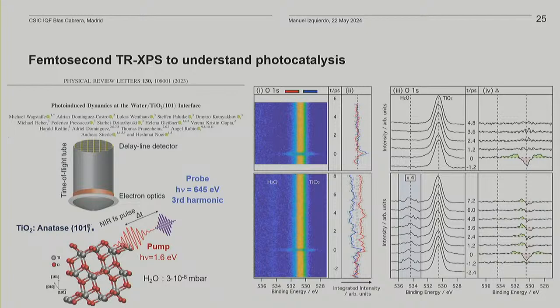And then in this case, when you shine with the lasers, you see that there is a change of the binding energy of the material. This is not related to surface photovoltage; this is related to the fact that, with the hydroxides on the sample, there is going to be a charge or hole transfer from titania to water that results in this chemical shift.